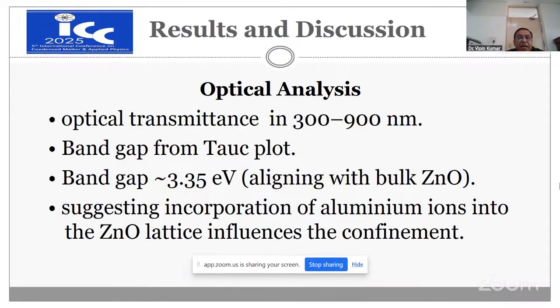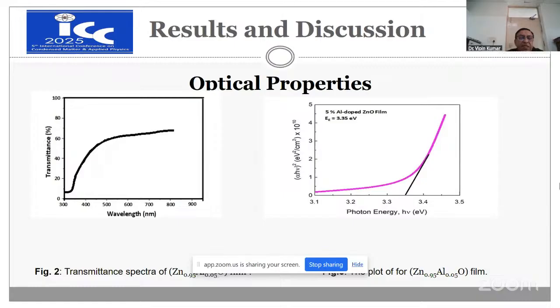And now the optical analysis. Optical transmittance in the range of 300 to 900 nanometer. Bandgap was calculated through the Tauc relation. Bandgap was found to be 3.35 electron volt, aligning with the bulk ZnO, suggesting incorporation of aluminum ions into the ZnO lattice influences the confinement. This is the transmittance spectra of our film, and this is the Tauc plot by which we calculated the bandgap equal to 3.35 electron volt.